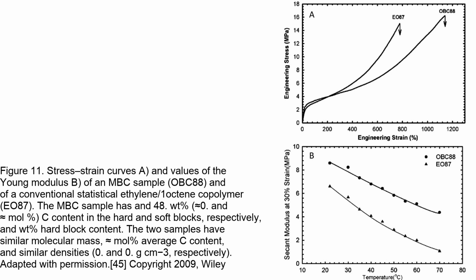Figure 11 in the paper shows stress-strain curves and the values of the Young modulus for an MBC multiblock copolymer sample compared to a conventional statistical copolymer. The MBC sample has a non-uniform chain architecture due to the compositional heterogeneity occurring at inter- and intra-chain level.